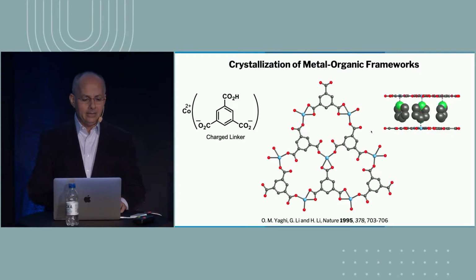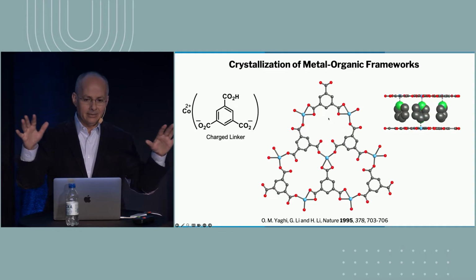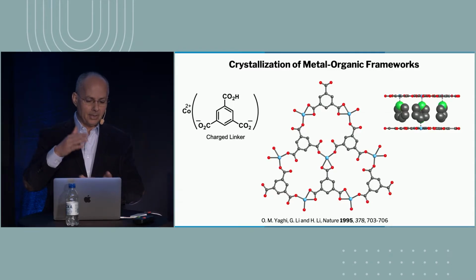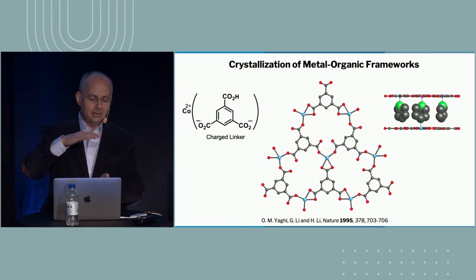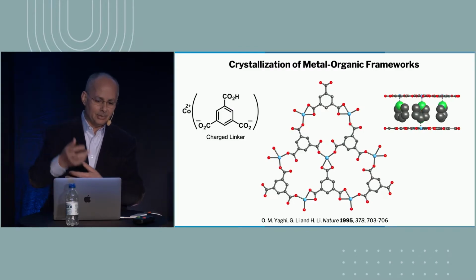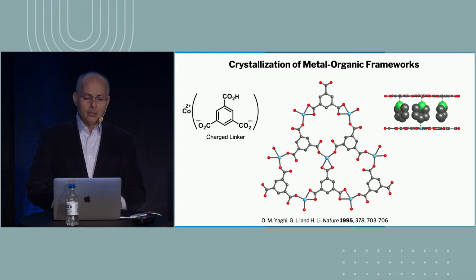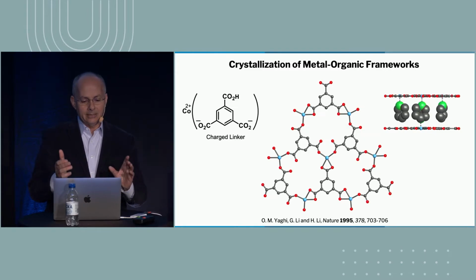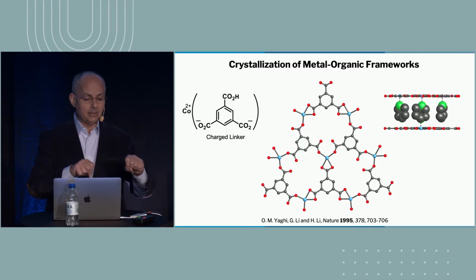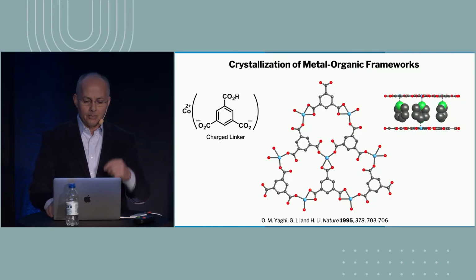So what in the end worked was linking a transition metal ion with a charged organic linker like this. And to make an extended structure, this is infinite, it's a layer, and between the layers, a pyridine, part of the reaction conditions, sticks between the layers, and we were able to take the pyridine out and put it back in and things like that. But again, this was the very first time that somebody could crystallize a metal organic compound linked by these strong bonds. So, but we wanted to develop this